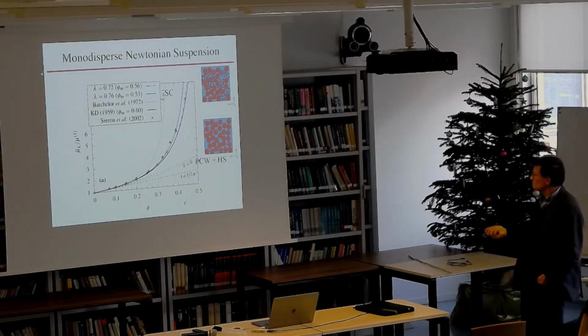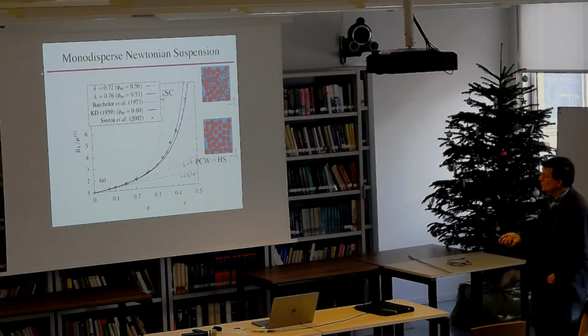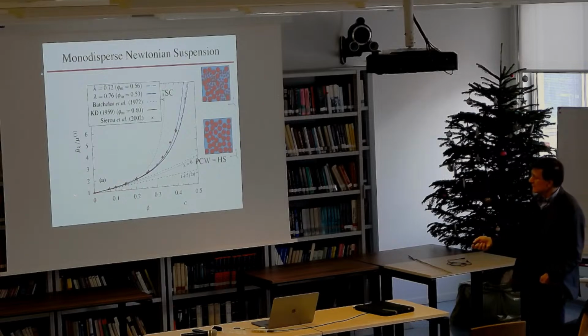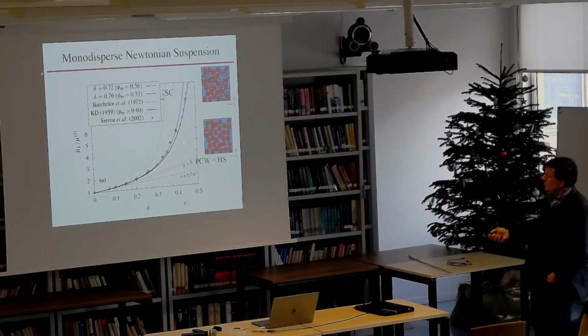If you plot the Hashin-Shtrikman or PCW estimates in this case, they're this dashed line, which does pretty well here - this is the Eshelby type result. But down here, it's a lower bound, and it's not very good at say something like 40% volume fraction.